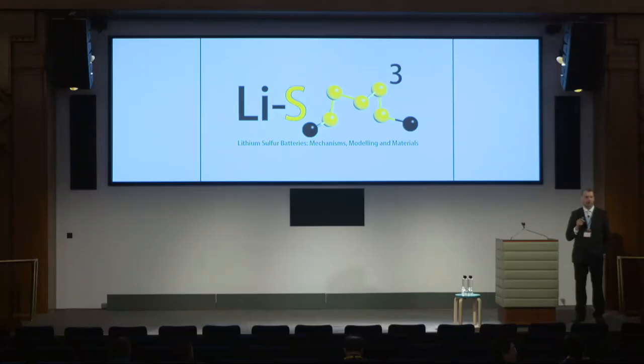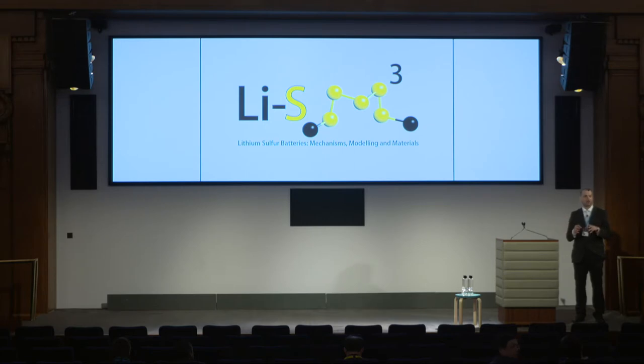Question from the audience: Why do you think the cell re-heals itself over time — do you have some extra gas volume inside the cell? This is exactly what I mean by constructing a very good operando cell. A coin cell has dead volume, so electrolyte can be pushed out of the cathode material but can also flow back in because the electrolyte will always try to wet the surface. At lower C-rates you are not pushing the electrolyte out as much. The new versions have no dead volume at all and are pressed together like a plate-type capacitor, so we hope to get much more industrially relevant results.